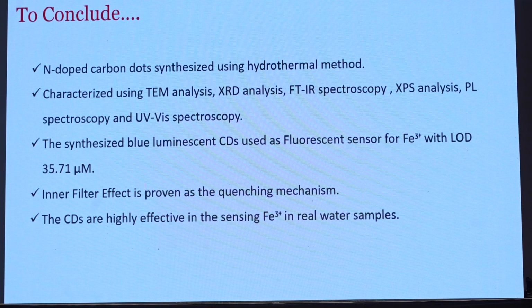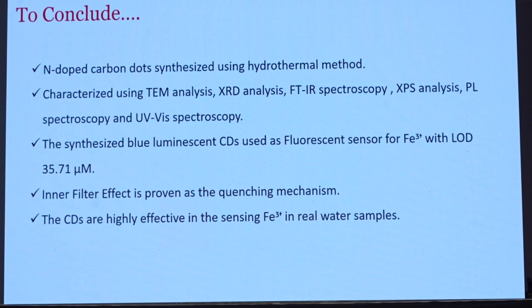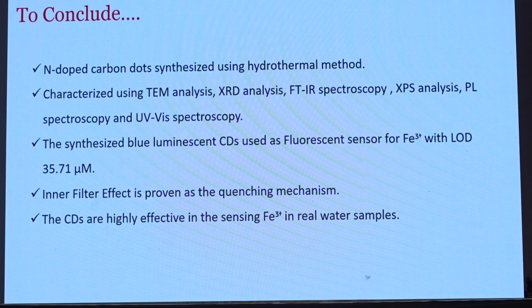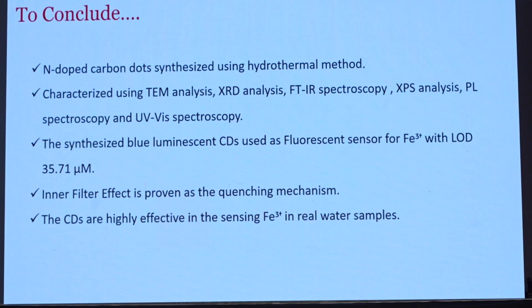We have synthesized nitrogen doped carbon dots using the hydrothermal method, and it is well characterized using TEM, XRD, XPS, FTIR, and PL spectroscopy. The synthesized carbon dot is used as a fluorescent sensor for ferric ion with a limit of detection 35 micromolar, and the inner filter effect is proven to be the mechanism of quenching in our system. And the carbon dot is effectively used for real water sample analysis.